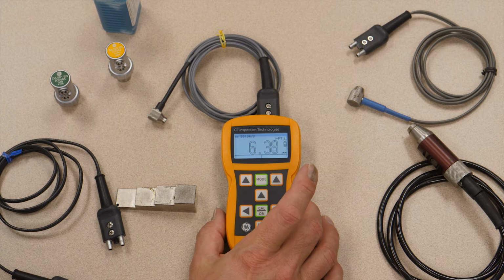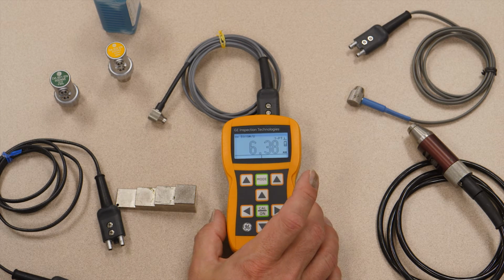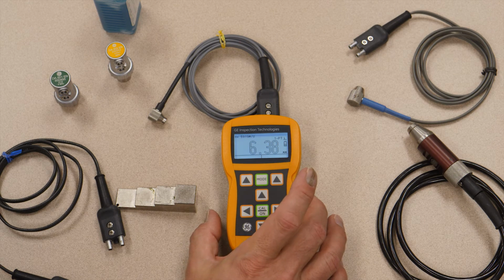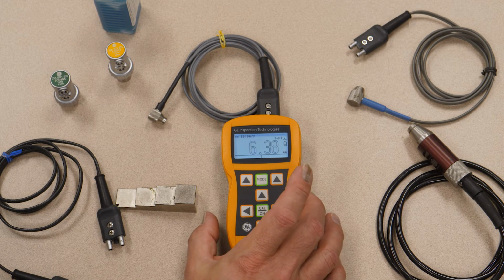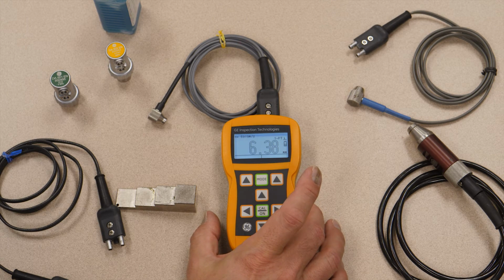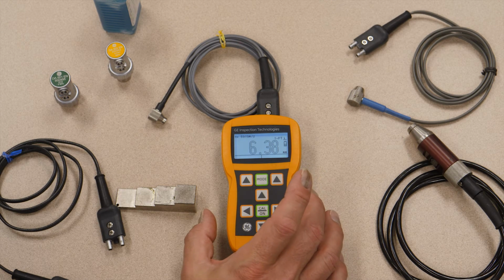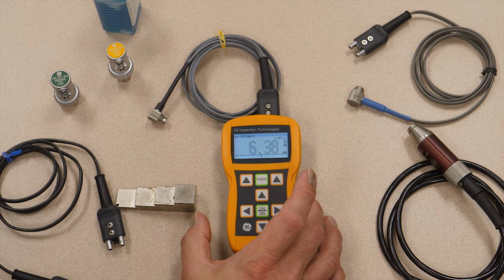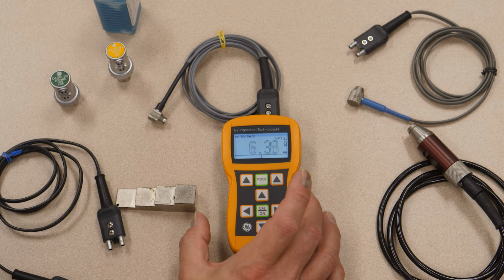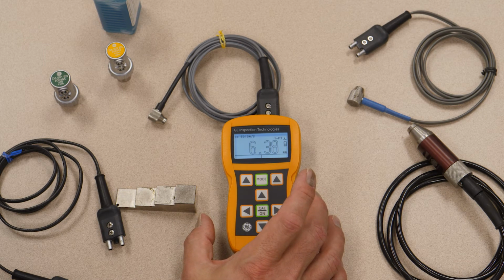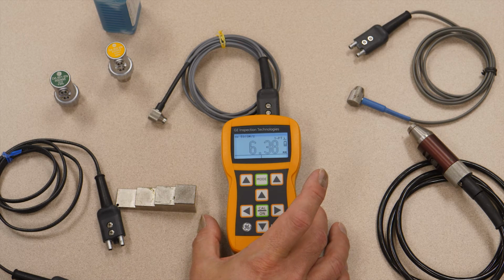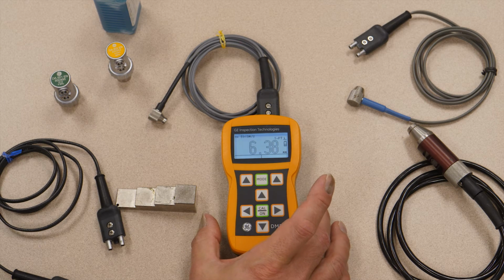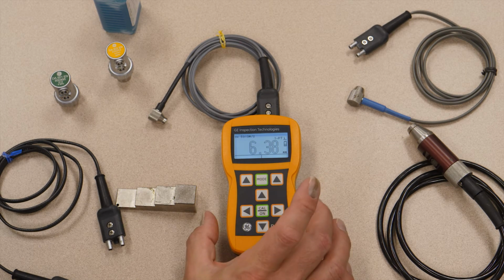The other option that's available in this instrument is dual multi-mode. And what that does is provide the capability to take measurements through coatings. So if you have painted material, if you have epoxy coatings on material, you can easily take thickness readings through those coatings. However, the coating thickness in normal dual mode will be added to the thickness of the base steel. So it's going to throw your reading off, and because the paint is typically about one-third of the sound velocity of steel, 10 thousandths of paint will increase your thickness measurement by about 30 thousandths of an inch. So we offer the dual multi-mode to compensate for that.